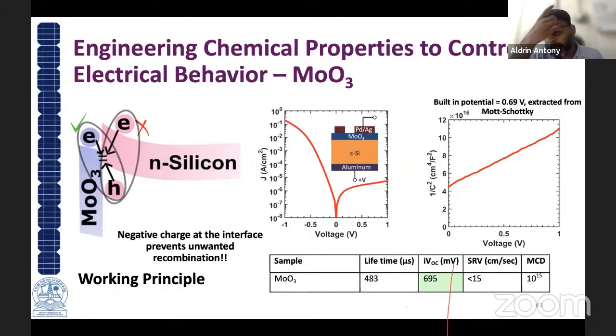For normal crystalline silicon solar cells, the open circuit voltages are around 630 millivolt, apart from heterojunction. Heterojunction solar cells have open circuit voltages in the range of 720 to 750 millivolt. So this was very impressive, because we just need to thermally evaporate MoO3, and then you get a very good passivation effect. That is why it shows a high lifetime, nearly 500 microseconds, and a possibility for a higher open circuit voltage for the solar cell.